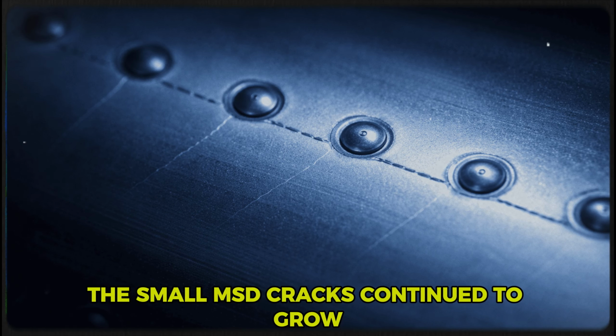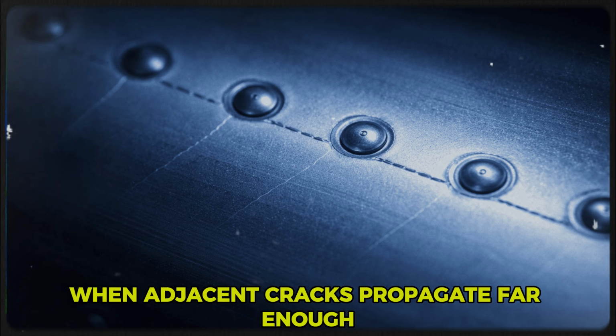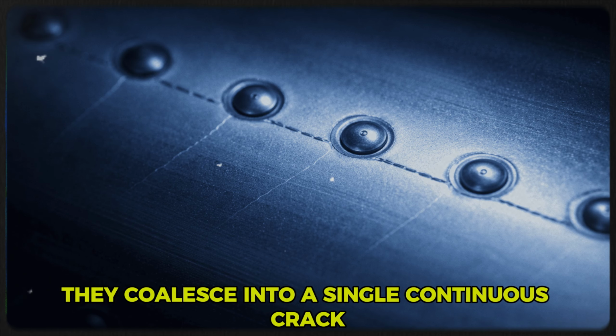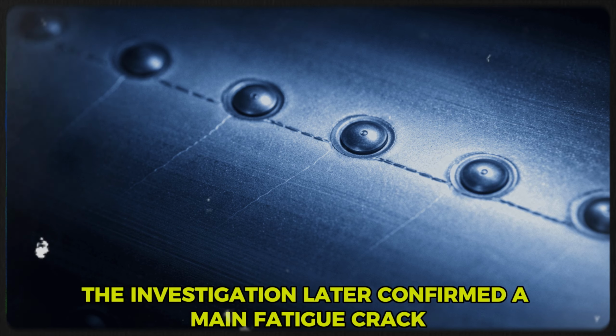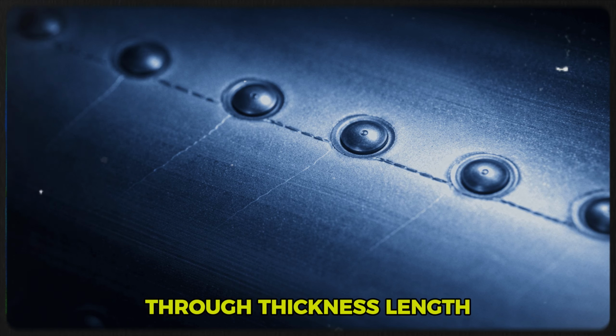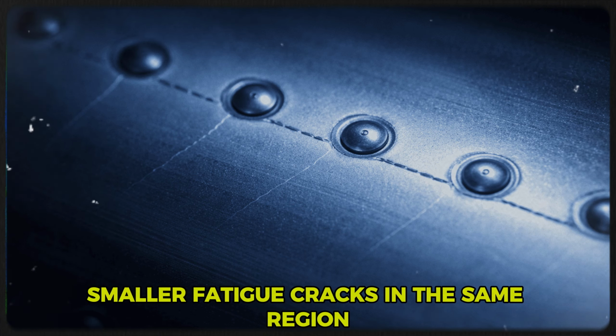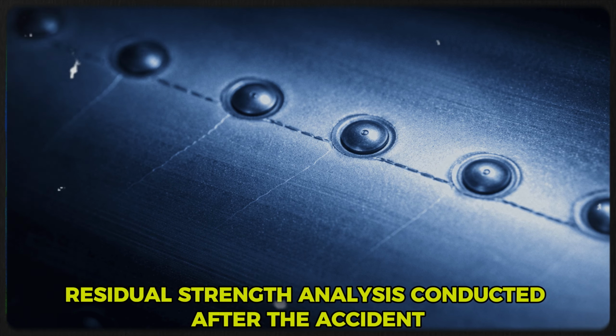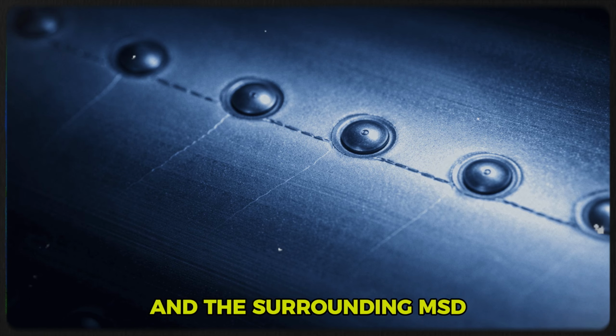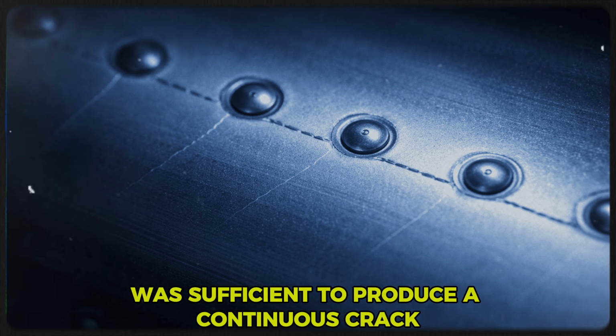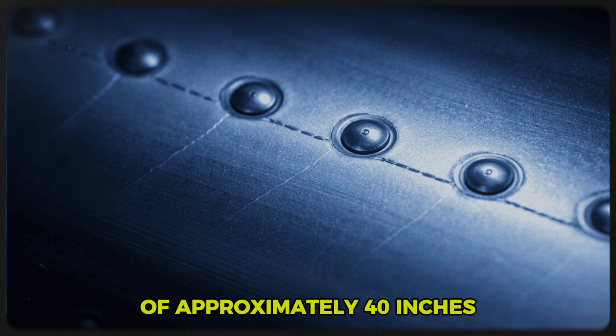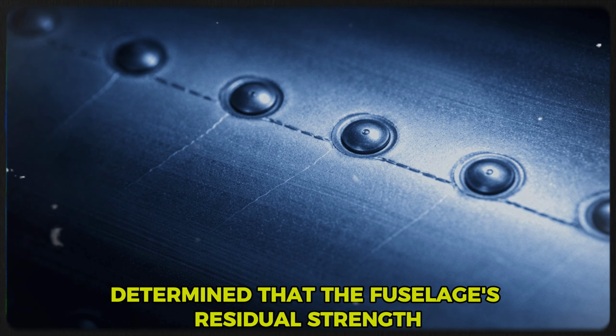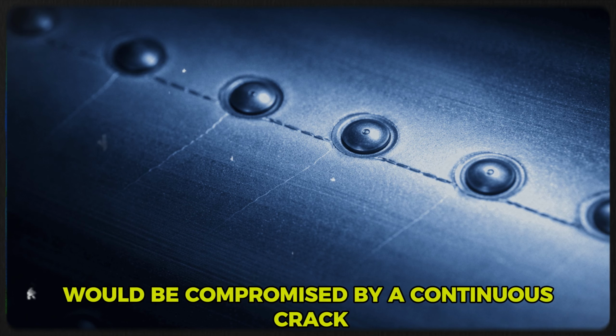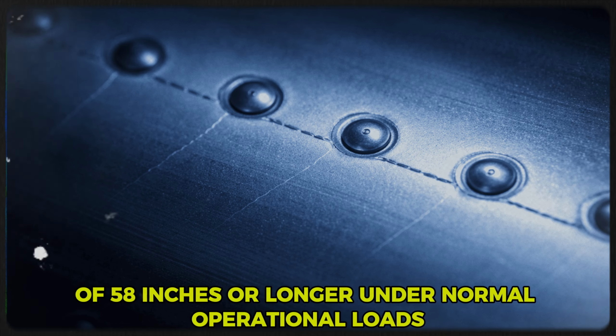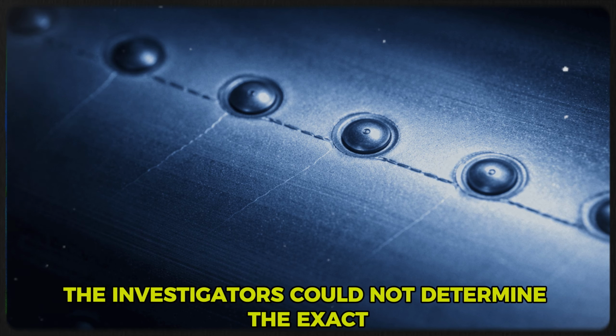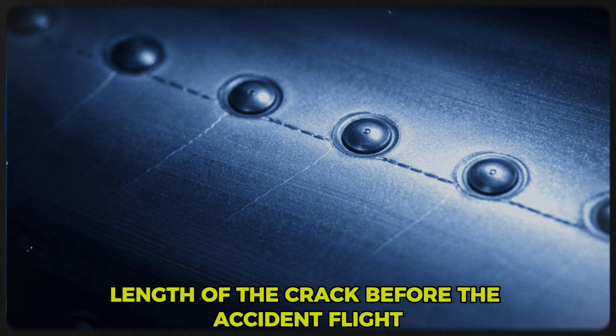The small MSD cracks continued to grow and began to link. When adjacent cracks propagate far enough, they coalesce into a single continuous crack. The investigation later confirmed a main fatigue crack of 15.1 inches in through thickness length, along with multiple smaller fatigue cracks in the same region. Residual strength analysis conducted after the accident indicated that the combination of the main crack and the surrounding MSD was sufficient to produce a continuous crack within a two-bay structural region of approximately 40 inches. Further analysis determined that the fuselage's residual strength would be compromised by a continuous crack of 58 inches or longer under normal operational loads.